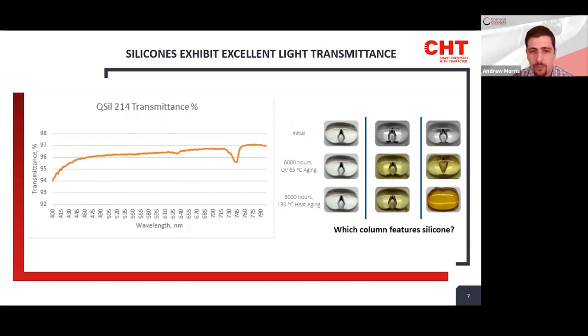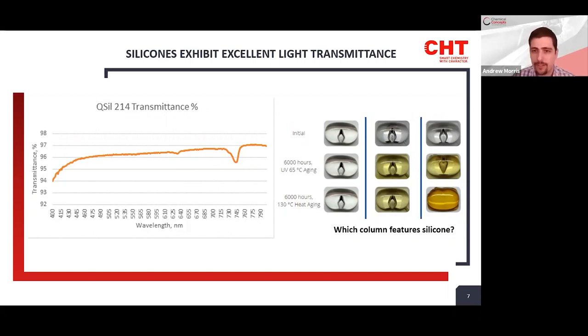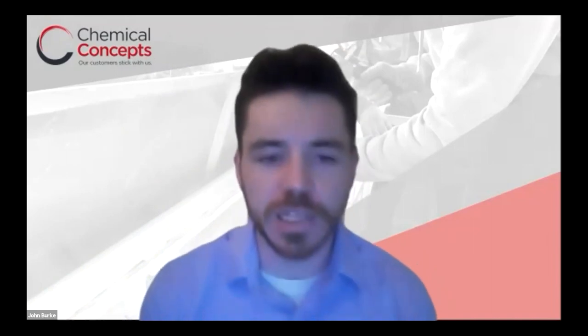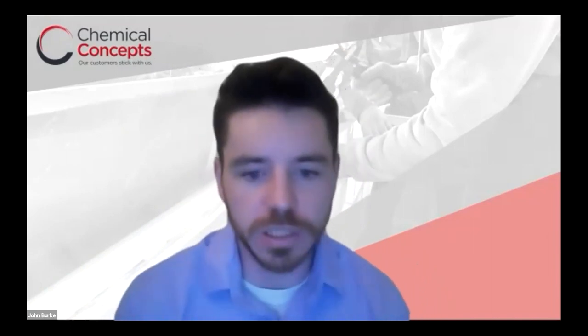And I can add that CHT has sent plenty of samples in the past and they can test that for you too, just to give you a heads up. Another question: will the silicones degrade in UV? Silicones themselves will not degrade when exposed to UV — whether from outside or from the light itself. You can see that in the transmission rate. If you're looking for applications below the 450 nm range, we should have some more discussions, as the transmission rate drops off at lower wavelengths. But for general exposure to the sun, they will not degrade.